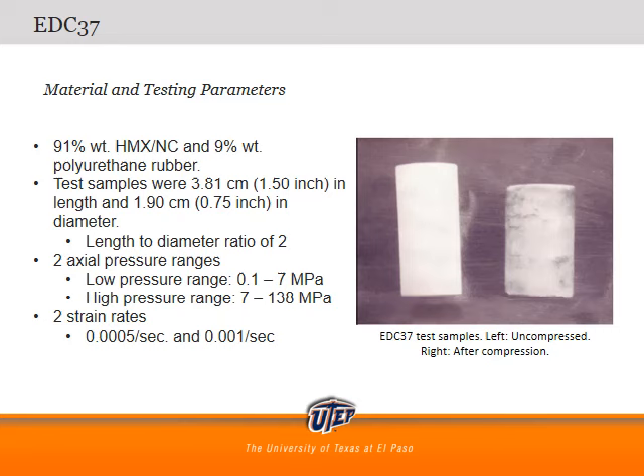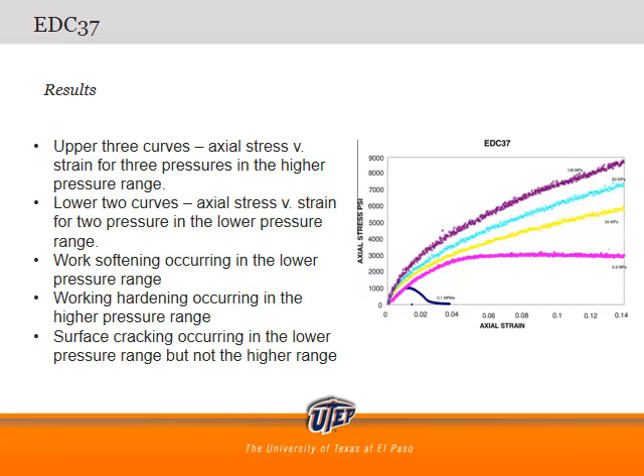All the test samples have a length to diameter ratio of 2. 2 axial pressure ranges were used in the experiment. The low pressure range is from 0.1 to 7 megapascals, and the high pressure range is from 7 to 138 megapascals. Both pressure ranges were subjected to 2 strain rates, which are 0.0005 per second and 0.001 per second. In the graph to the right, axial stress versus strain for 5 pressures is plotted. The upper 3 curves correspond to 3 pressures in the high pressure range, and the lower 2 curves correspond to 2 pressures in the lower pressure range.